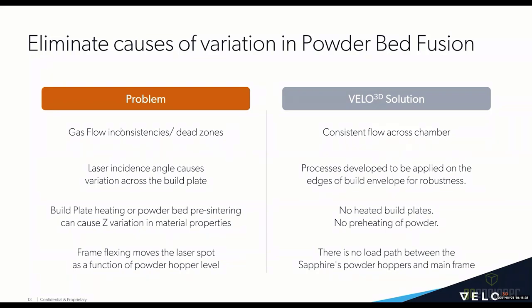So first off, in the X and Y direction, we have gas flow inconsistencies. Dead zones are a common problem. We have consistent gas flow across our chamber. We don't have any obstructions like recoaters in the way, et cetera. Additionally, laser incidence angle can cause variation across the build plate. And for the VELO3D processes, they're qualified and developed not only directly underneath the laser, but also at the extremities of the build plate, so that day in, day out, you don't see that variation with respect to location.